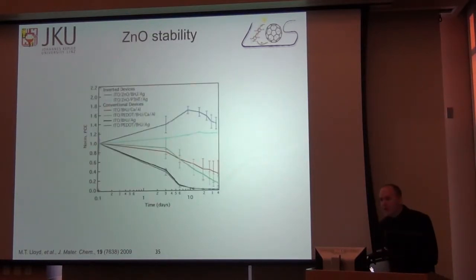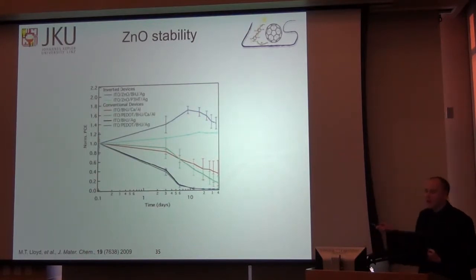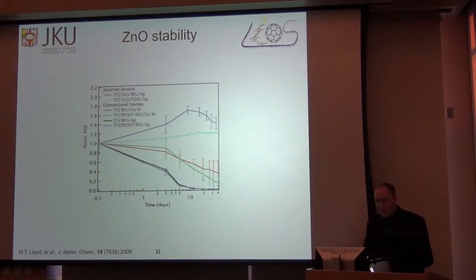But the real interesting part is that if we subject these devices now to a shelf life durability study, the zinc oxide devices not only outlast their conventional counterparts, but they improve significantly upon exposure to air. So by replacing this air-sensitive device, we were able to make devices that we could store and use in the lab for all kinds of purposes for years even. So here we show this up to about a month, but we can make devices and store them in the lab for about a year, and they work as well or better than they did when they were fabricated.